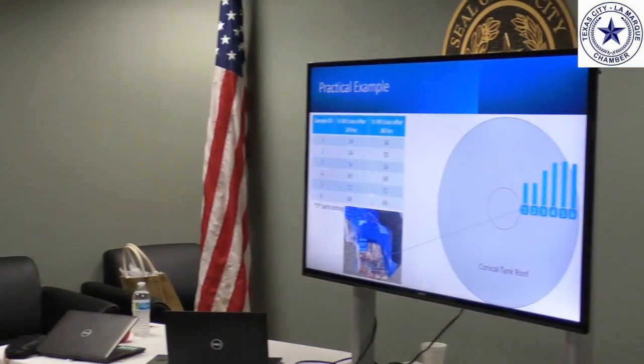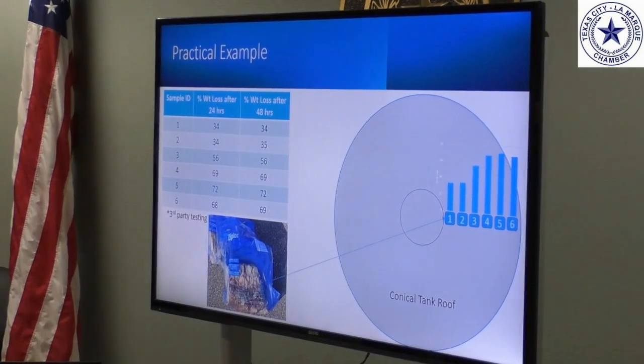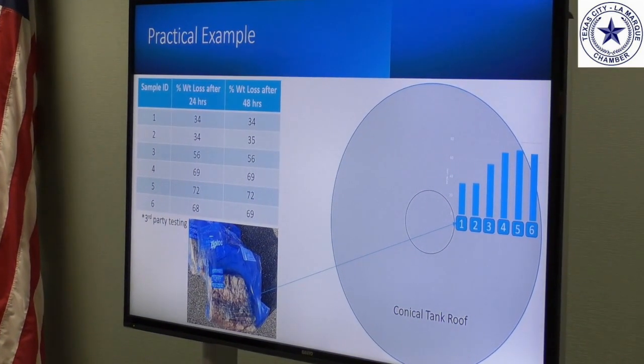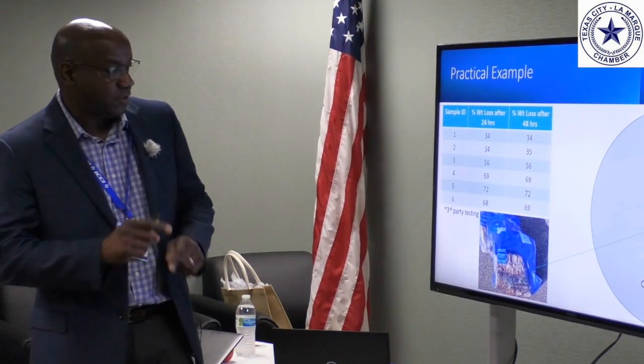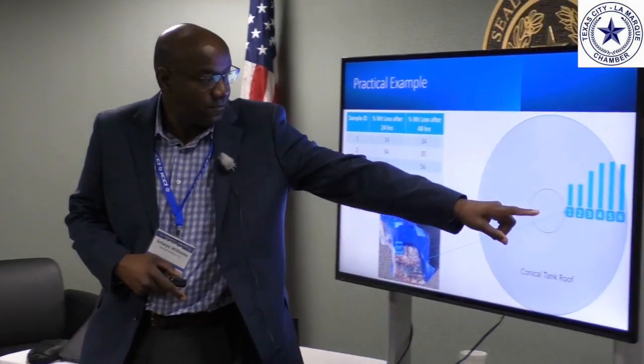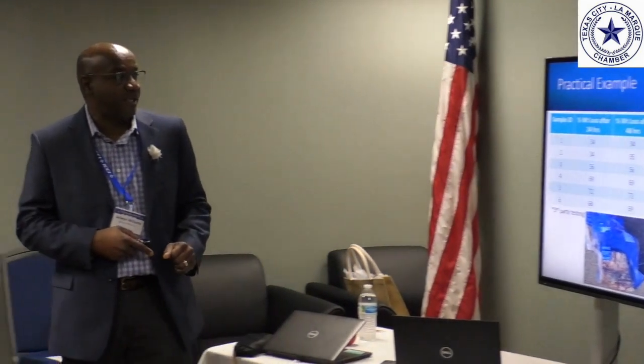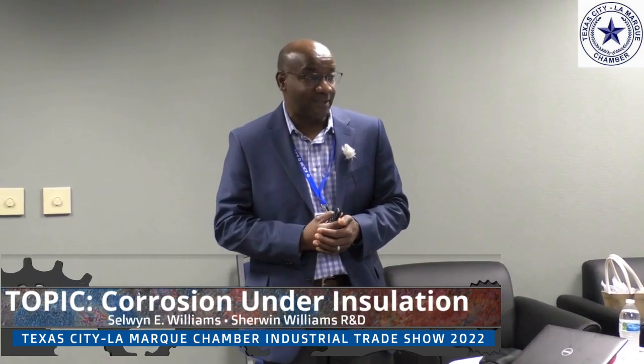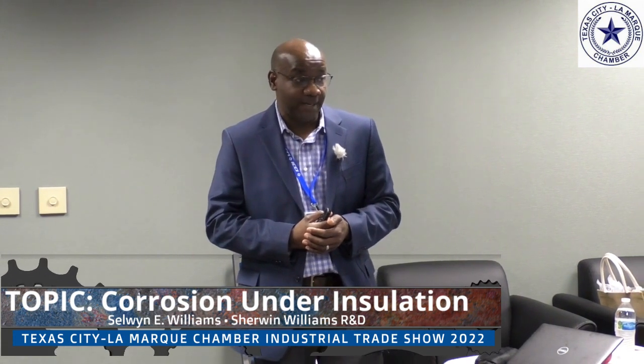Practical example. Again, we did have some collaboration with one of our industry partners, and they allowed us to measure water content across a conical tank roof at one of their facilities, and the measurement tells us that there's a lot of water in that roof. They were about to replace this roof, and they allowed us to go on site and pull samples. We sent the samples to our third-party lab, and these are the results that came back. So the tank is sloping outwards. So we had at position 1, 34% water by weight in that sample of insulation that we took, down to 69% water at the lowest point. So again, water is your enemy.